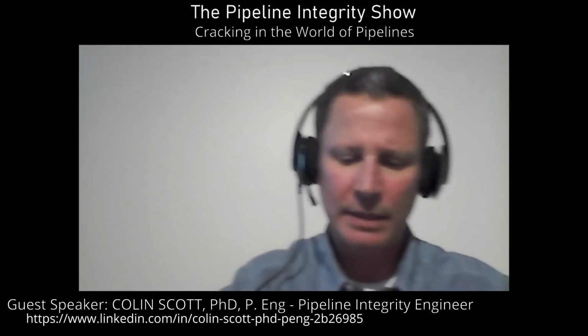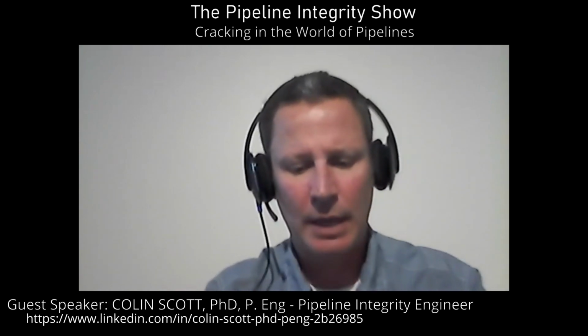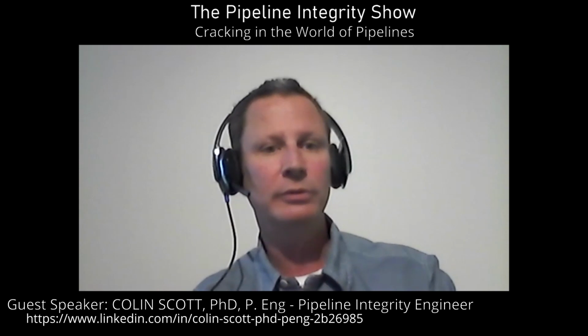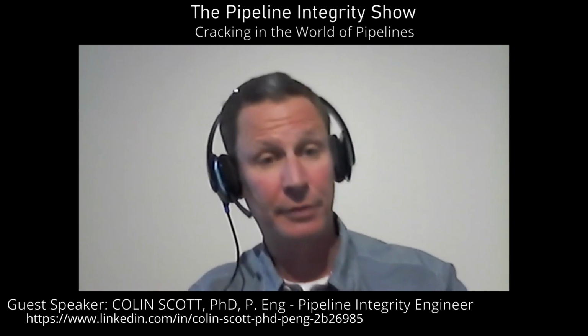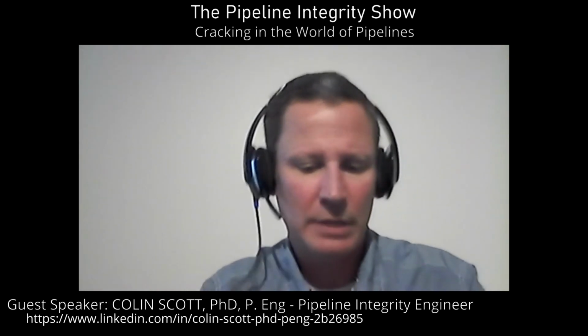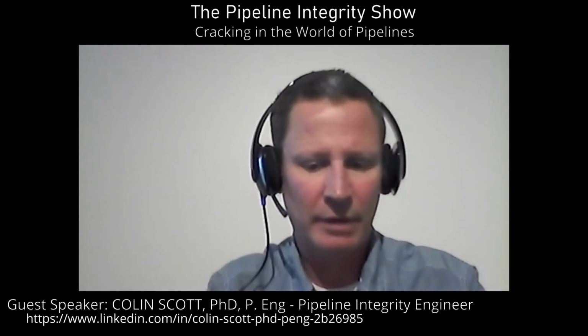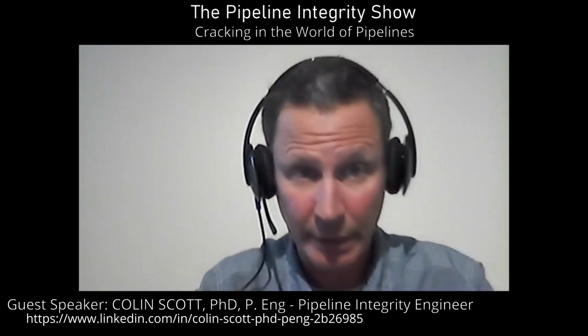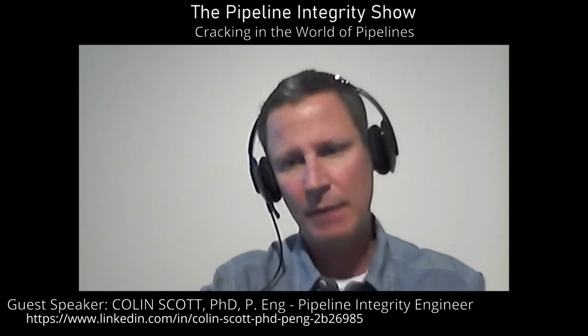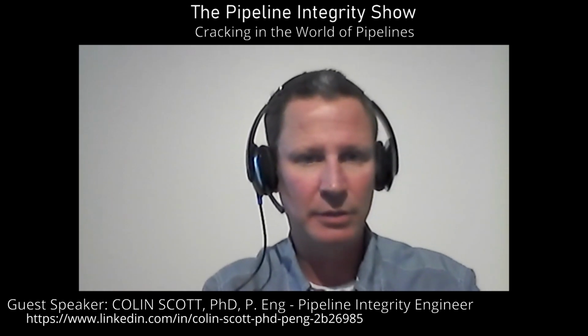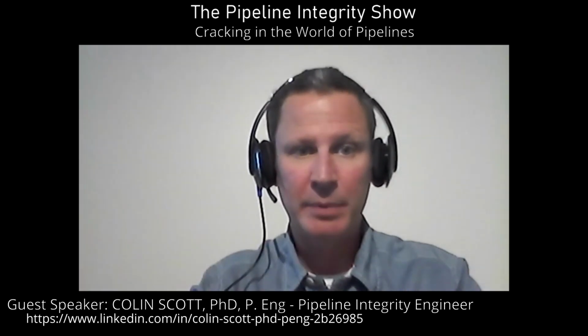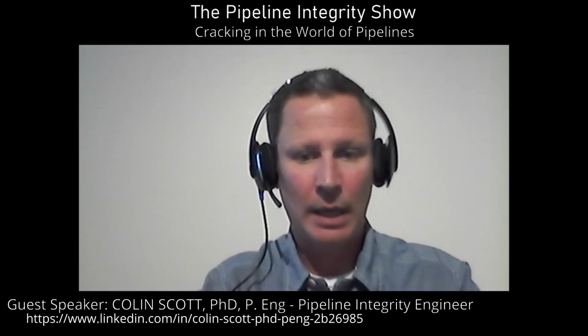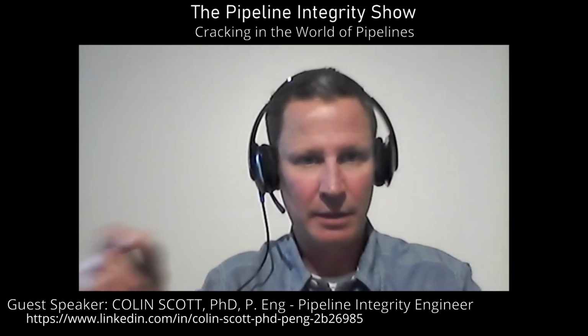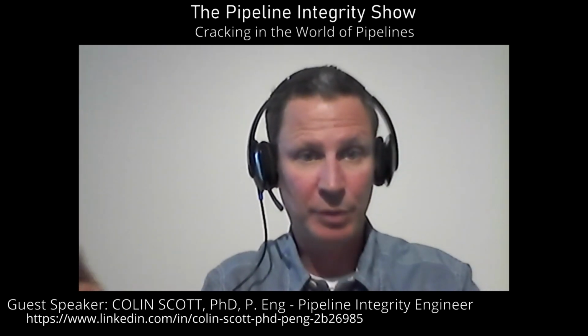And then the second thing that I took a look at for this operator really relates back to what we talked about a few minutes ago with the inline inspection tool vendors and their sizing algorithms. If the tool vendors can say we have a depth of plus or minus 1 millimeter 80% of the time, then you can probably say to yourself, statistically speaking, you've got plus or minus 2 millimeters, I don't know, maybe 98% of the time. And then that last 1% at each tail of the distribution represents plus or minus 3 millimeters, right?